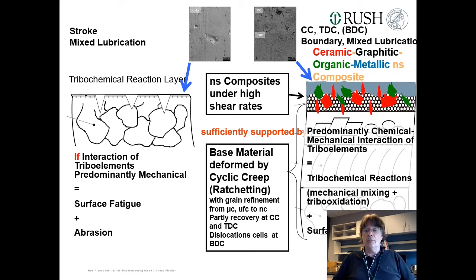And at the top dead center, we found the structure we already have seen with the FCC materials, as well as with the martensitic materials from the base material, which in this case had been nanocrystalline already. We found remains of a strain gradient, mostly in the bottom dead center, because at the top dead center, it's so hot that even dislocation cells start to recrystallize and vanish. But we always found these shear bands with incorporation of the interfacial medium and environmental stuff. So in this particular case, it was a ceramic, graphitic, organic, metallic, nanostructured composite. The thickness, by the way, was 50 nanometers.